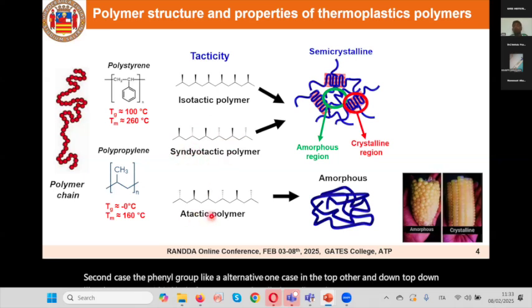In the third case, they can be arranged randomly. There is no particular order. That kind of tacticity is called atactic polymer. Now you can see that just by arranging the phenyl groups in different ways, the macroscopic properties completely change. The first two, isotactic and syndiotactic polymers, have a well-ordered structure. In one case they are on one side of the polymer chain, in the other they alternate. Because of the ordered arrangement in the polymer backbone, these two polymers can exhibit semi-crystalline phases. Semi-crystalline means a mixture of amorphous and crystalline. These kinds of polymers are called semi-crystalline polymers.